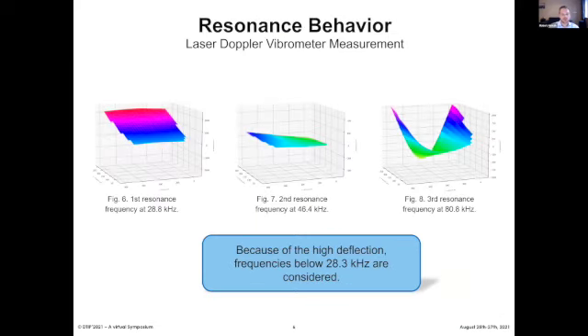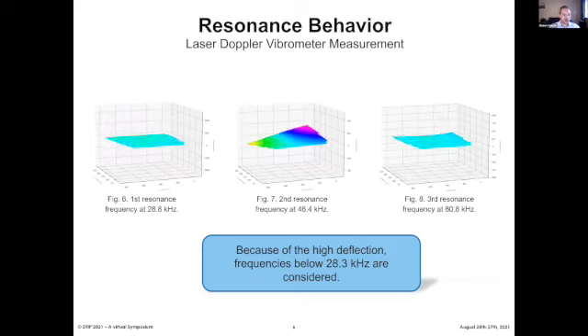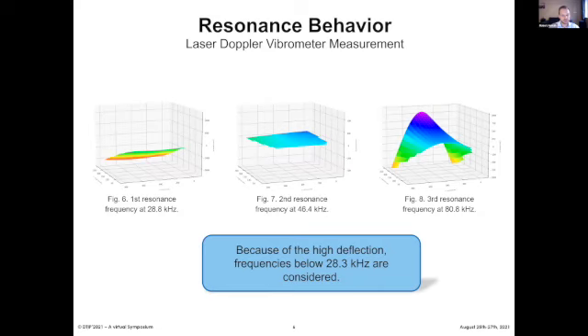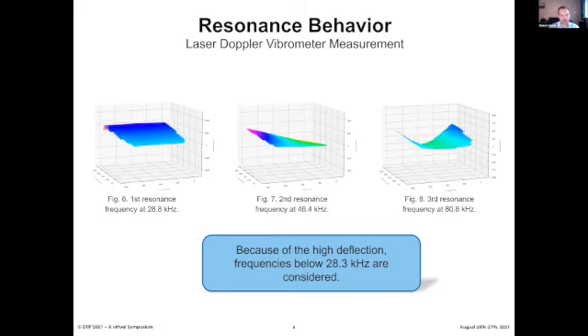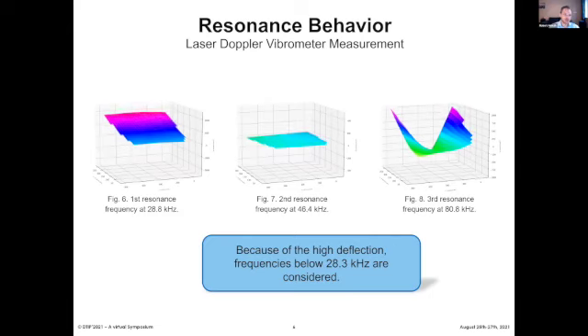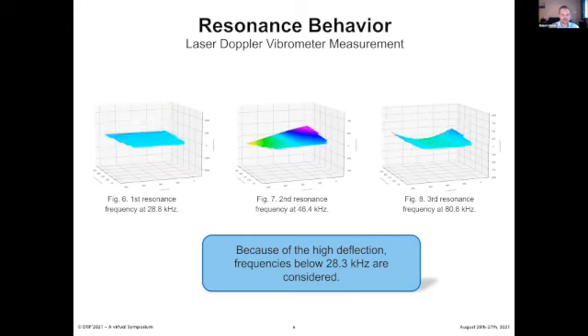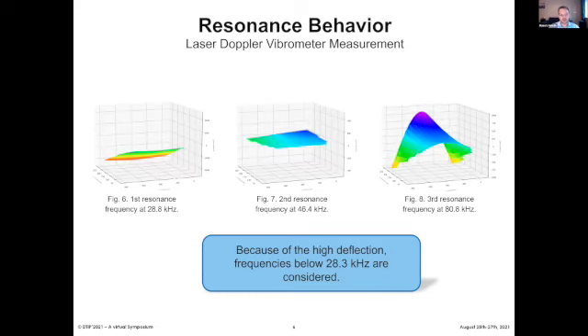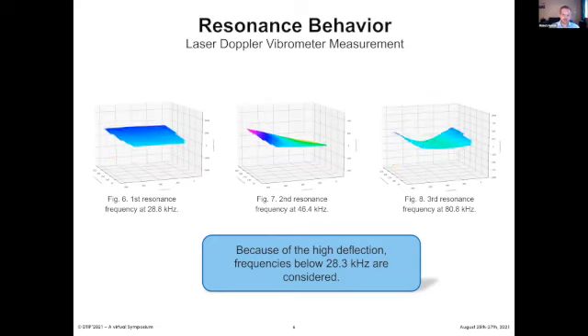And here we can see some measurements I've done with a laser Doppler vibrometer. Here we can see the first 3 resonance frequencies of the device. The first one is slightly below 30 kilohertz, and we can see the leading edge in front is moving just up and down, and the points move all in phase. For the second resonance frequency, we can see a strong twisting of the device, left to right. And for the third resonance frequency, the device is bending really strongly.